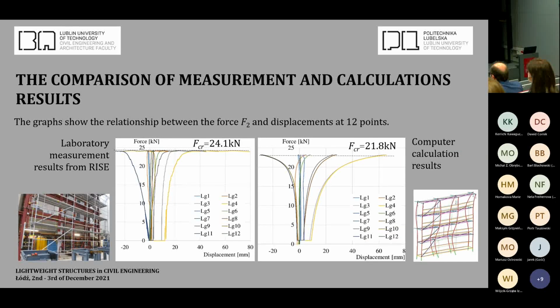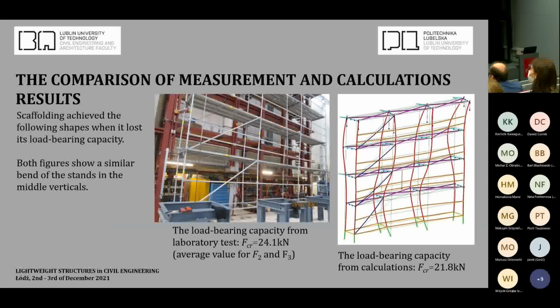And the results, the laboratory global test and calculation results. The main results are displacements in 12 points as a function of the forces. Force, or forces, because we have the same vertical force which is applied here. The scaffoldings achieved the following shapes. It lost bearing capacity. Both figures show a similar bend of the stand in the middle vertical. And the load bearing capacity from calculation is 10% smaller than the critical value from the laboratory test.